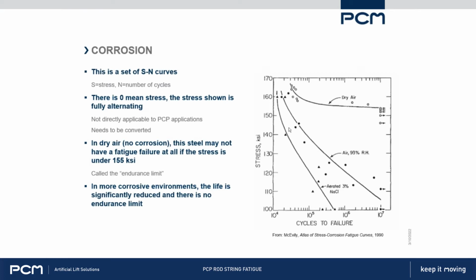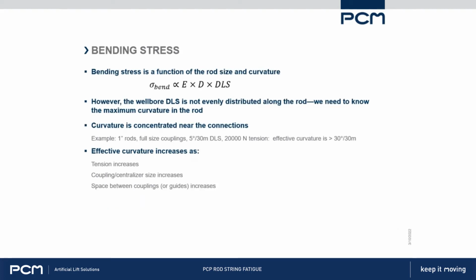And again, this is an SN curve that's for fully alternating loads. It's not the same as what we see in a PCP application. We need to do a conversion to make that work. So the bending stress, this is what's happening each rotation of the rod as it goes from tension to compression and back. The bending stress is a function of the rod size, so the diameter, the curvature of the well, and also the material property. Now with steel, all the different grades of steel have approximately the same Young's modulus or modulus of elasticity. So really that's not going to have any effect when you're choosing different rods. So it's the diameter and the curvature.